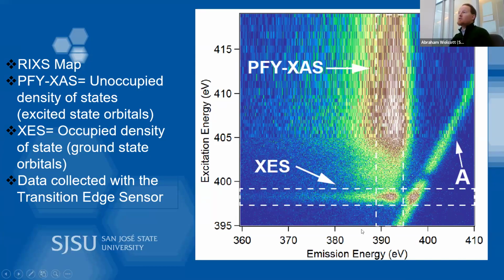What does this produce? You can get something like this. This is a resonant inelastic X-ray scattering map. So you would change the excitation energy while looking at the emission energy on your system. The unoccupied density of states is provided by our partial fluorescence yield XAS. So you integrate counts vertically. If we want to know about the occupied density of states, our ground state orbitals, then you integrate your counts to generate your X-ray emission spectroscopy data set. So you get almost everything all at the same time. So it's quite powerful.